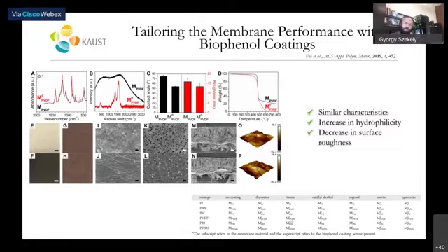Instead of going into all the details about each individual data, I will just show you all of these characterizations and just focus on the main message. Here you can see that the surface of the membranes is quite smooth, and if you look at the cross section, you can see the huge macro voids in the membrane structure, and we have a very dense support on the top of the membrane that is the active layer.